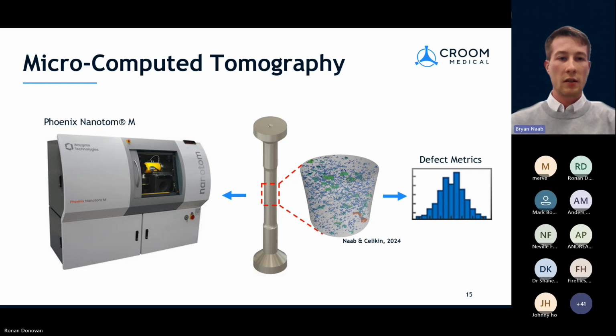Essentially, we can scan a part and it will create a number of X-ray images, and it will reconstruct those X-ray images into a three-dimensional model. This is very useful because it can tell us exactly where defects are present, and we can do data analysis to extract key metrics about these defects. Specifically, we can identify the maximum critical defect within the material, and this can then feed into our quality inspection metrics for AM parts. It's particularly useful for validation of processes.